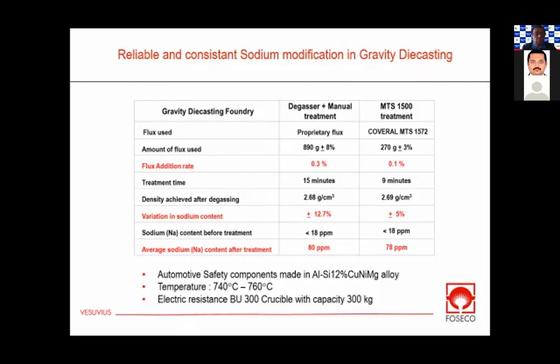And here is the case, but the problem with sodium is you have to lose a lot of sodium, you have to use a lot of flux. So we've developed an application where basically we can reduce the addition rate of the sodium.